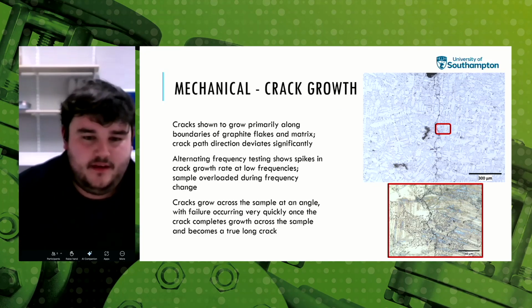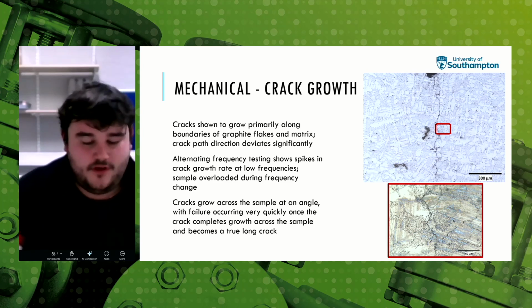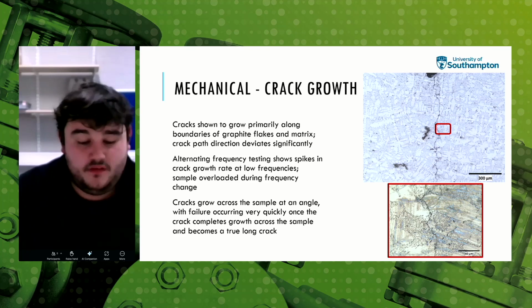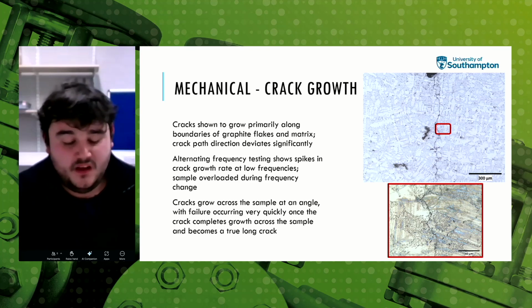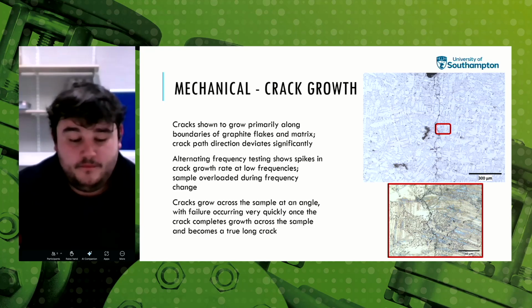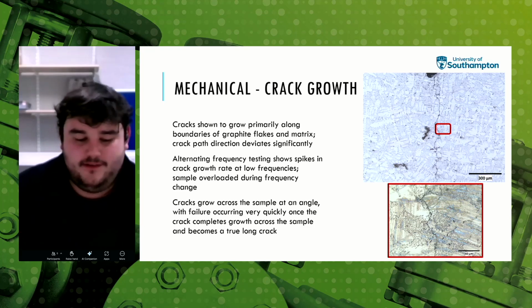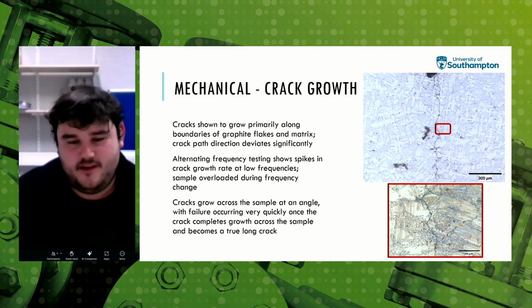In this sample here, you see a crack growing down from the notch. And as you can see, the crack follows the graphite flakes through the microstructure, jumping flake to flake and minimizing the amount of pearlite the crack has to break through. Again, this reinforces the idea that the strength of the pipeline can be directly related to the proportion of pearlite present in its microstructure.